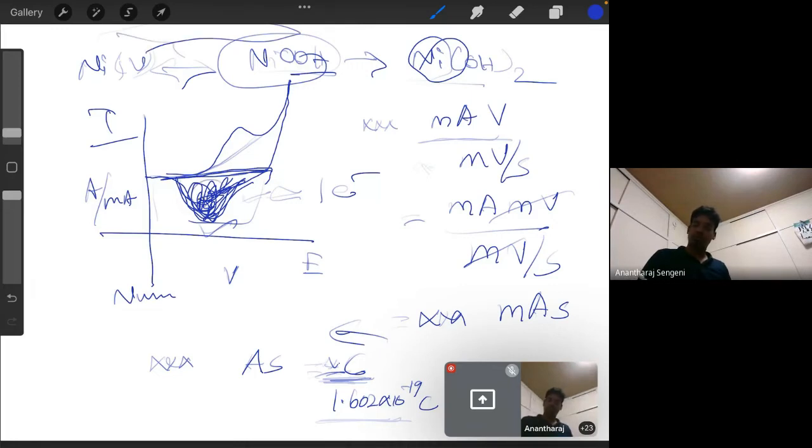And we will always miss this proportion of nickel, but we would be calculating something which involves both of these couples. So when you have more than one metal and one metal is affecting the redox behavior of another metal, never use this method. That is what I would say.